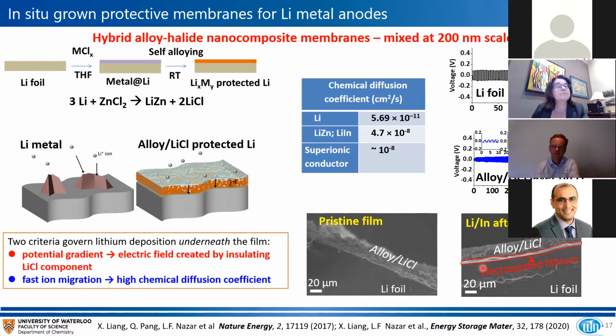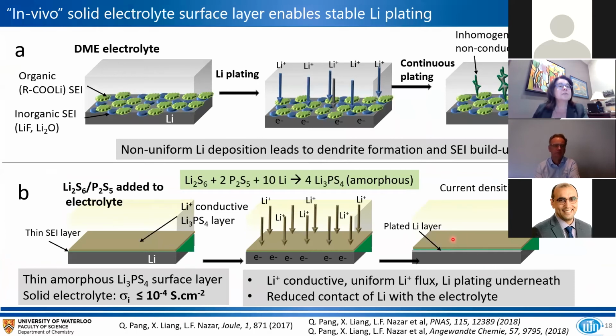So we then extended this concept to more traditional electrolytes, which in this case is lithium thiophosphate. And it's a well-known solid state ion conductor with very modest conductivity. But the point here is that by adding these precursors to the electrolyte and allowing them to react with lithium, we form an amorphous version of this lithium thiophosphate, again, directly on the surface. So sort of analogous to the alloy, but now we just simply have a solid state conductor.